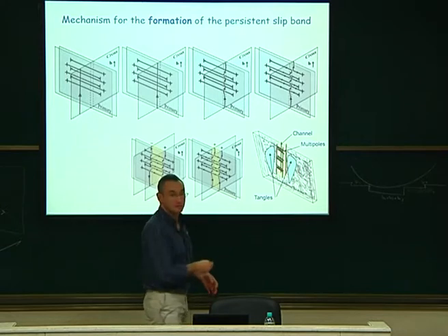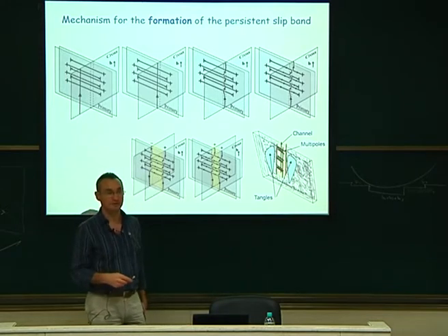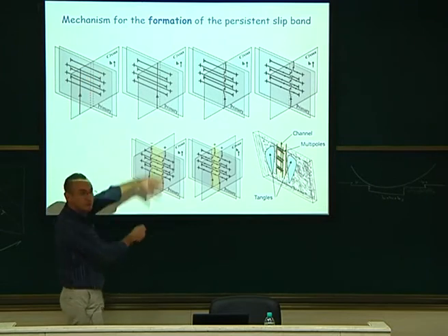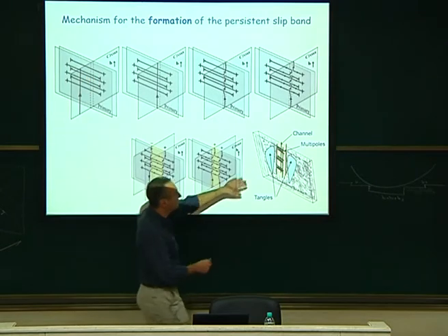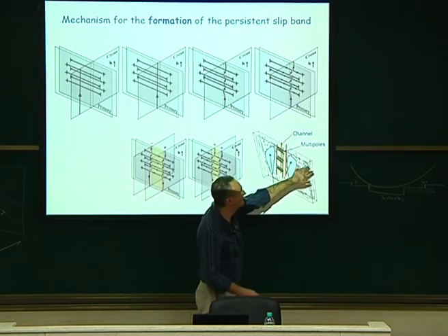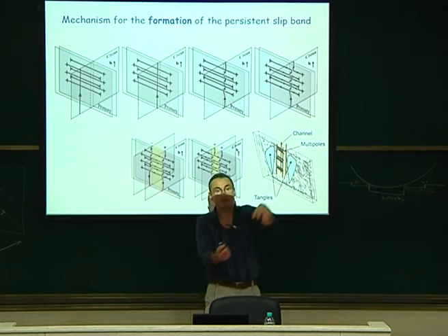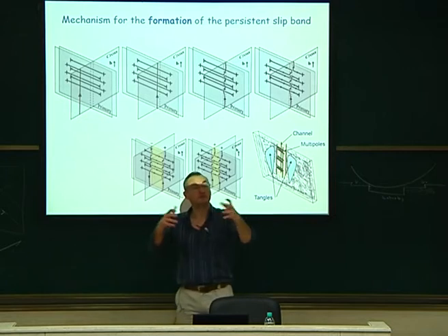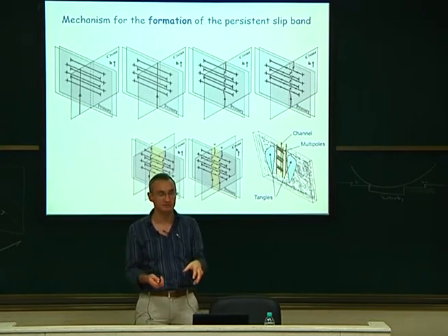And there, just because the veins are also separated. You see, the vein structure is not everywhere. You have this dipole. This came from the initial dipoles you formed. So you had some dipoles here, another dipoles there. They cannot be at the same place because the dipoles also repel each other. So there's a kind of screening effect of the dipoles in the simulations.